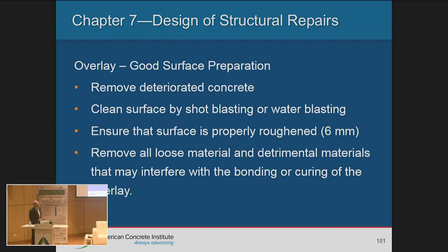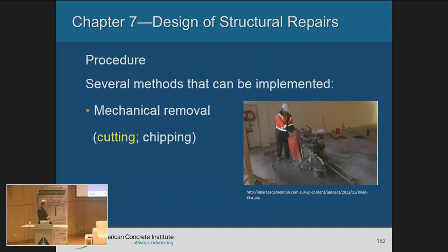So they want to remove all the deteriorated concrete, clean the surface by blasting or water blasting, and ensure that the surface is properly roughened. What we mean by roughening is the difference between the high points and low points of the roughened surface. So you need to have highs and valleys, so that when you add your overlay, they bond properly together. You don't want it to be smooth when you remove concrete. If it's smooth, that means it's not good surface preparation. Good surface preparation is when you have those highs and lows in your concrete. A good number is about 6 millimeters. And all the loose material needs to be removed.